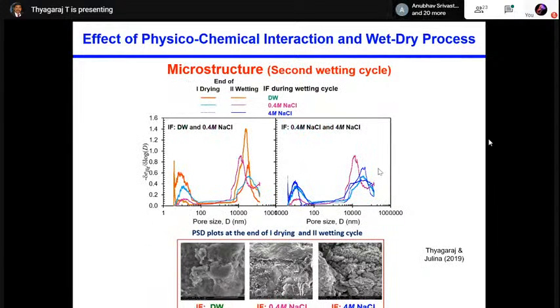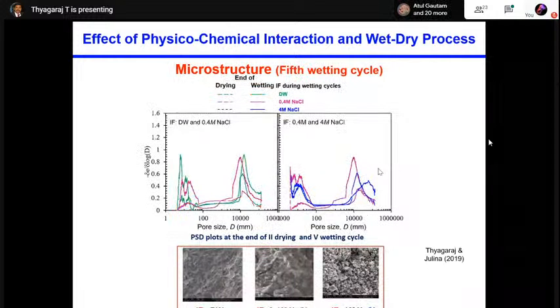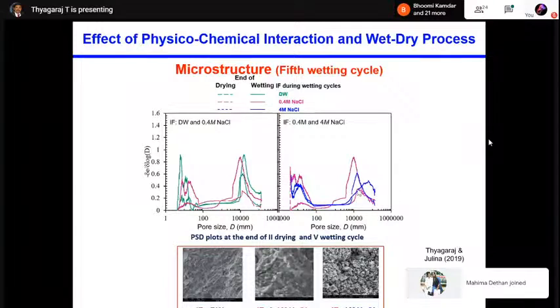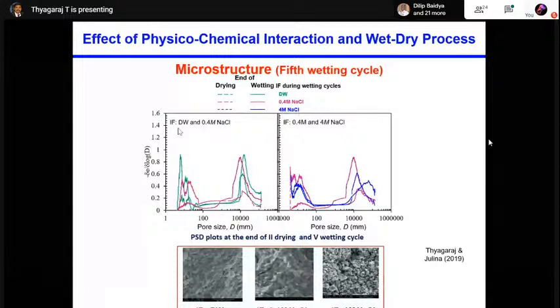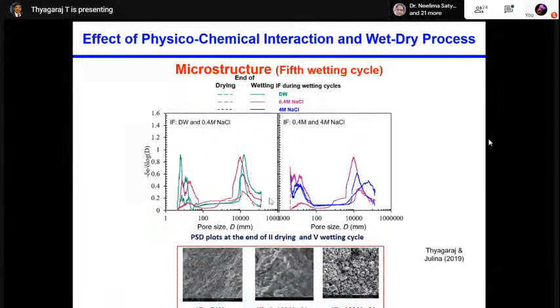Same thing can be observed during the subsequent cycle. I'm not going into the detail. I think I took more time in the beginning. Same thing can be observed even at the 5th wetting drying cycle. For example, at 0.4 molar solution, you can see here this one. And when we observe the 4 molar solution, you can see the macro pore size is increased with respect to the 0.4 molar specimen. So when we compared the distilled water and 0.4 molar, obviously the behavior was the same as we have seen there also. The same thing is conveyed in the SEMs as well.